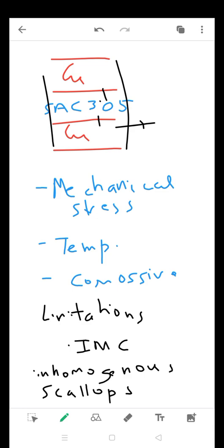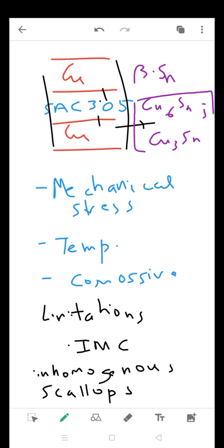Now what are the different phases which are possible at the interfaces? Since it mostly consists of tin, the beta tin phase is possible. Then you can have a Cu6Sn5 phase, whereas you can also have a Cu3Sn phase. Now these two phases are the ones that we are mainly concerned about. We don't want an inhomogeneous distribution of these phases. What we want is a homogeneous distribution. So the lower the number of these intermetallic compounds, the better the performance of these materials.